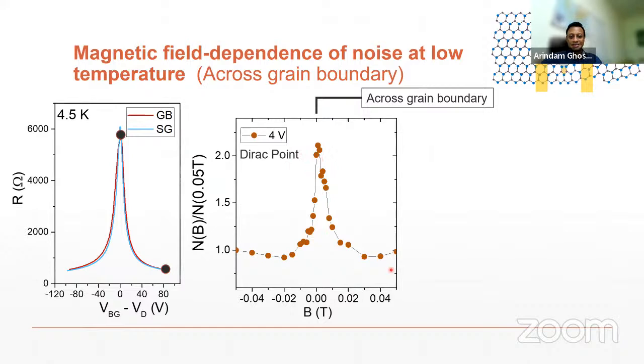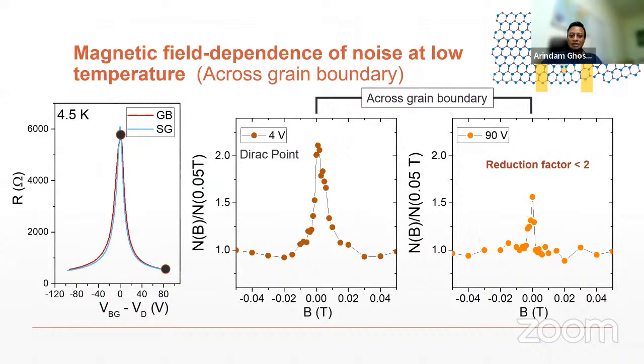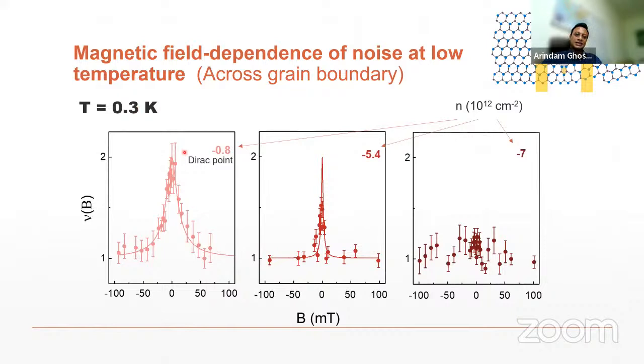But if I go here, somewhere here, then you can see noise is no longer coming down by a factor of 2, but it is just about 1.5 below. And this data was taken at 4.5 Kelvin. If I do the same experiment at 0.3 Kelvin, lower temperature, you can see that at the Dirac point, noise comes down by a factor of 2.